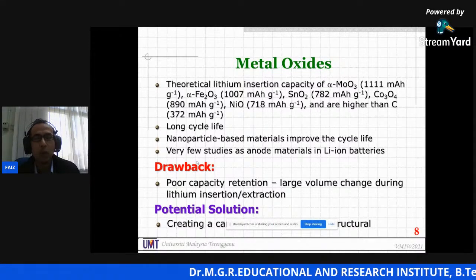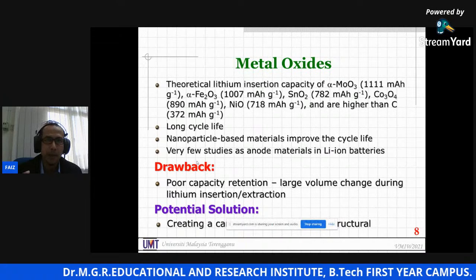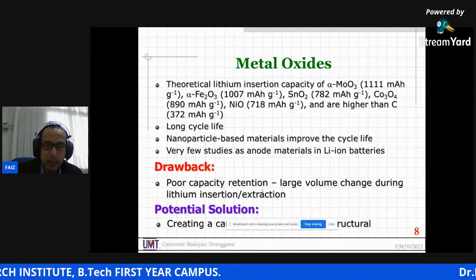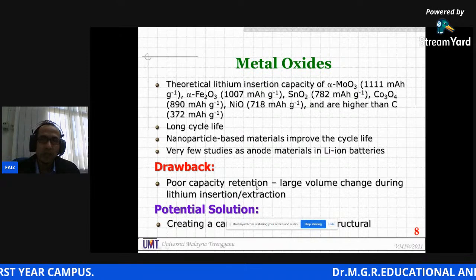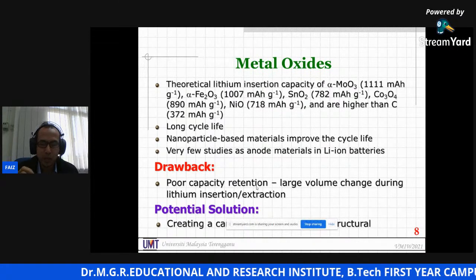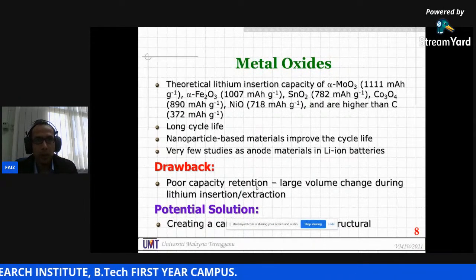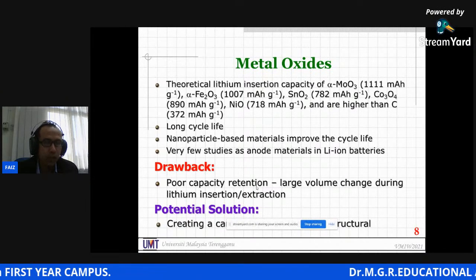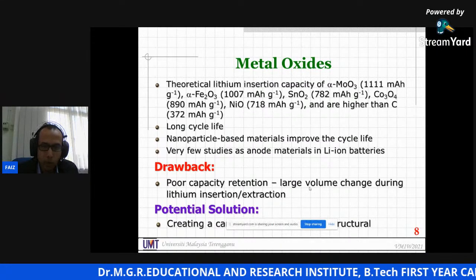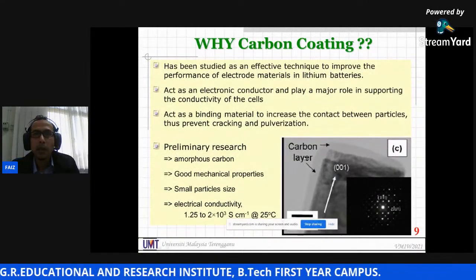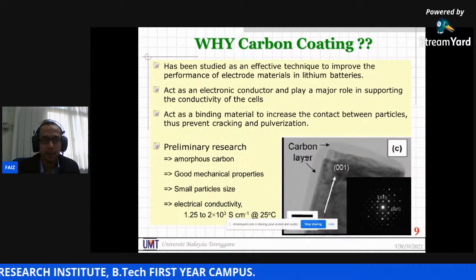However, from my previous study, I found only one obvious drawback of this metal oxide material, which is poor capacity retention, referring to the phenomenon where a large volume change occurs in the material structure during lithium insertion and extraction. One of the potential strategies to minimize this drawback is by creating a carbon layer on the metal oxide structure.